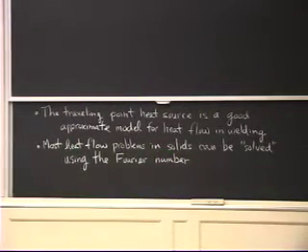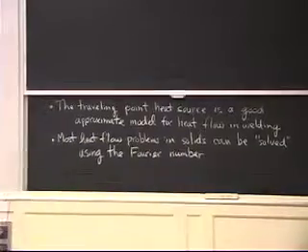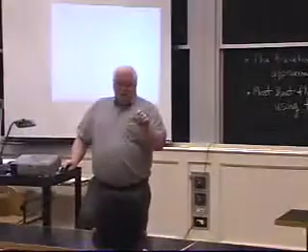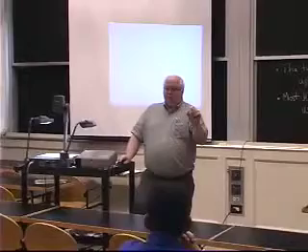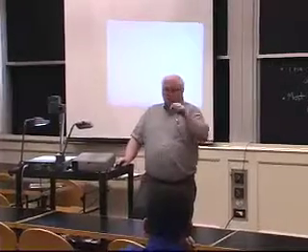When I say solve, most times you just want an approximation, and yesterday we went through and showed that if you look at the interaction time for an arc weld moving past a point, if it's a centimeter long and you're traveling, I don't remember what we said, at 0.3 centimeters per second or whatever, you can calculate that the heat affected zone size is going to be about 4 millimeters by just using the Fourier number. Okay, what we said was, I should probably put this up.